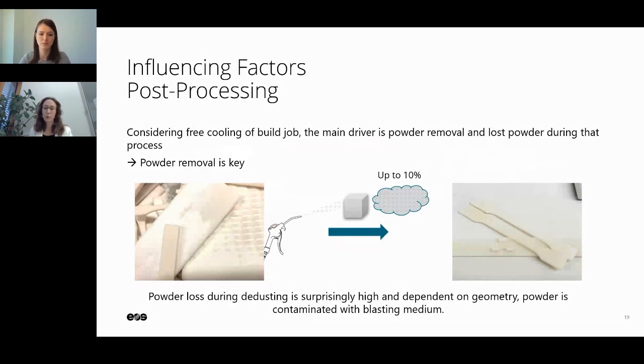And I have two problems with that. It's actually hard to get it out. And if I have blasted the parts and I have this residual powder blasted off, it's contaminated with the blasting medium. So even if I would like to reuse this waste powder, I have to separate it from the blasting medium. So this powder removal is quite a lever to even reduce the powder usage more, but we have to see how we can reduce the powder that's blasted off.